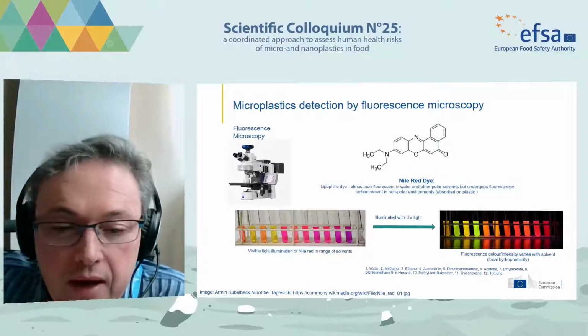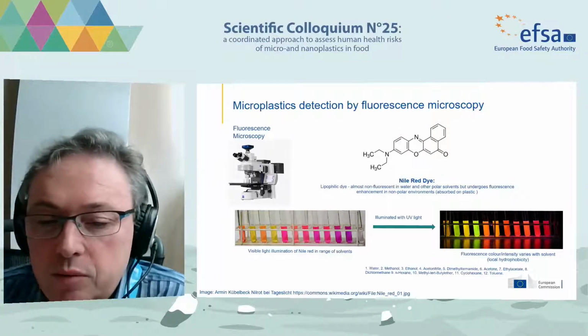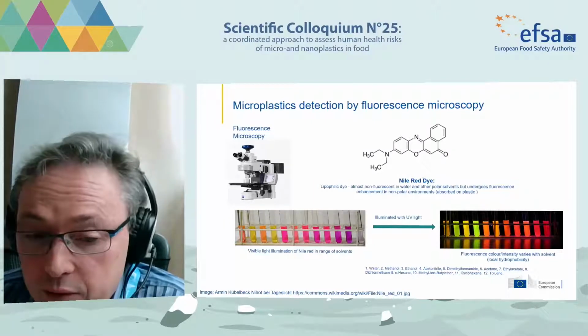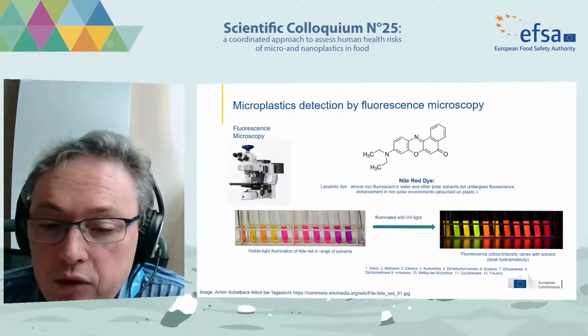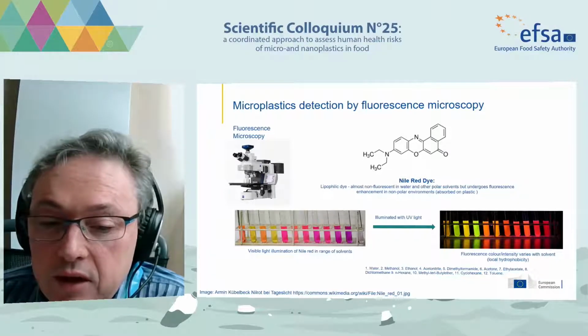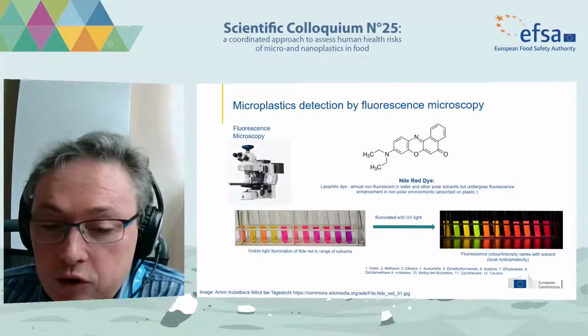The important feature of this dye is the fluorescent properties which change depending on the hydrophobicity of its local environment. In practice, the dye is weakly fluorescent in water, where the presence of more hydrophobic solvents increases the fluorescent intensity, as well as modifying the emission spectrum.